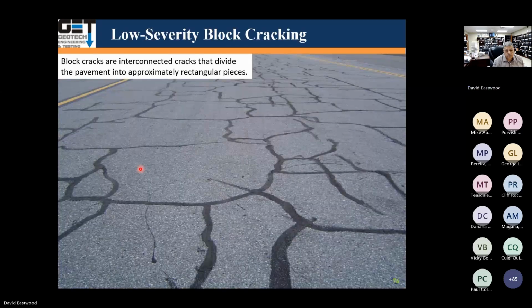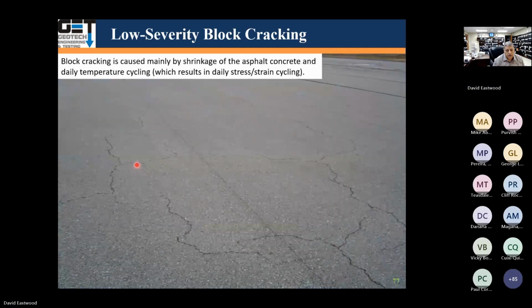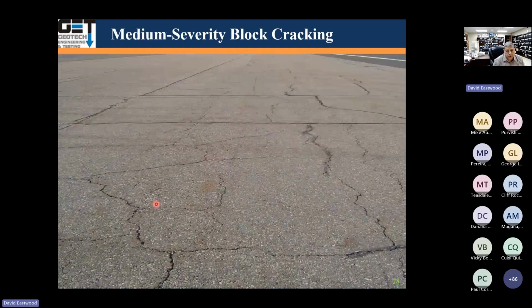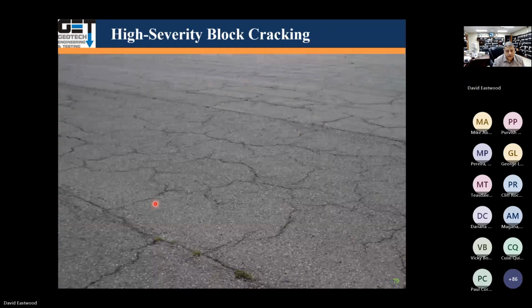So here's block cracking. Basically, interconnected cracks that divide the pavement into approximately rectangular pieces. This is a kind of a low severity block cracking caused by shrinkage of the asphaltic concrete and daily temperature cycling. Medium severity block cracking. High severity block cracking.